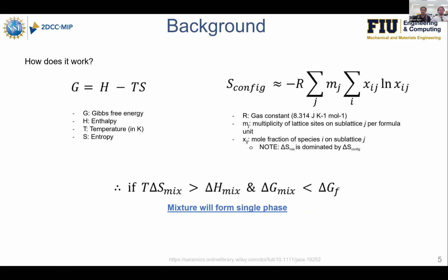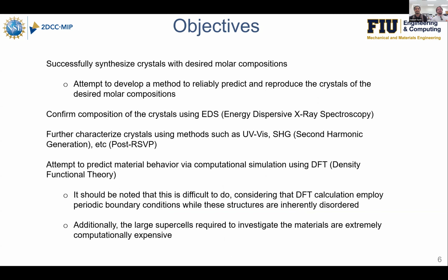And by adding those 6 to 7 elements into that crystal structure, we are greatly increasing that S term, the entropy, which in turn decreases the Gibbs free energy of the entire system. And because that Gibbs free energy is minimized, it makes it a lot more likely to form a single phase of the high entropy material that we're interested in studying. All right. For our project, our goal was to successfully synthesize the crystals with desired molar composition of each element and attempt to develop a method to reliably reproduce these compositions.